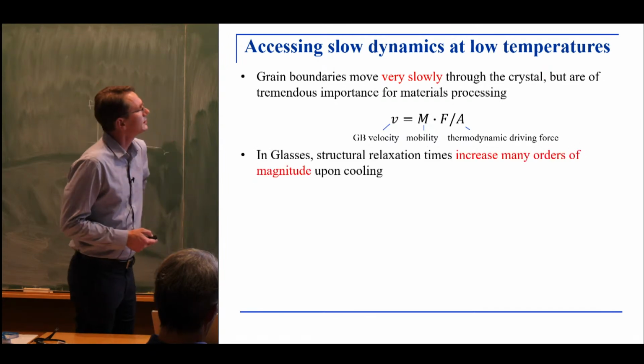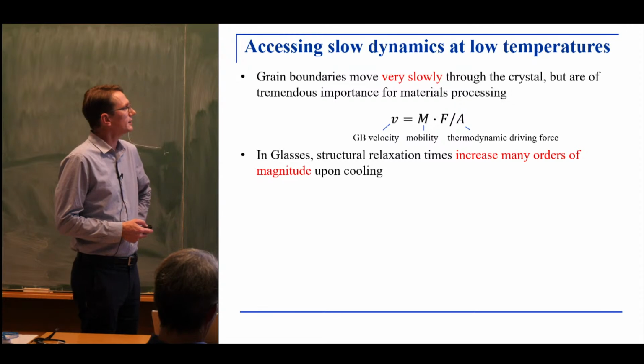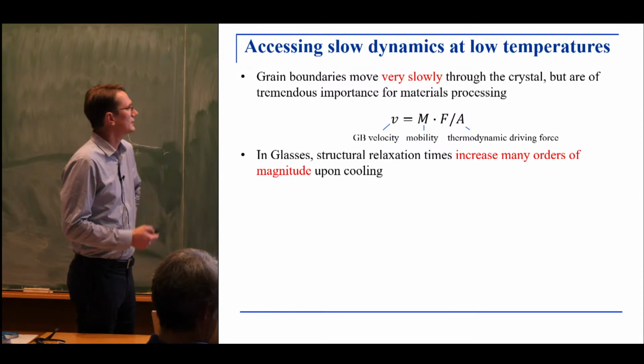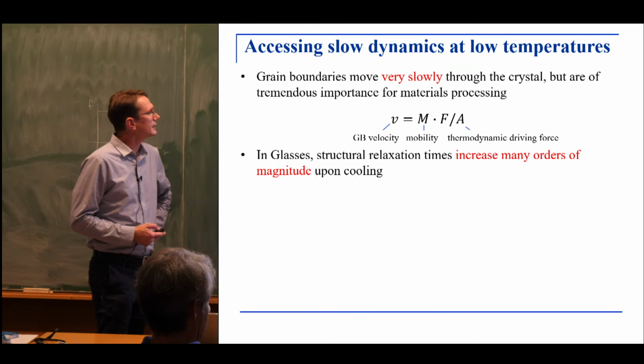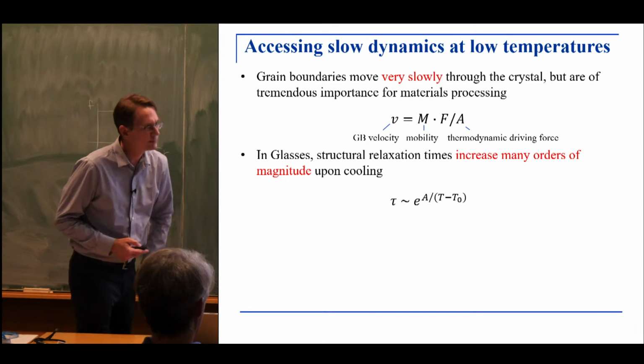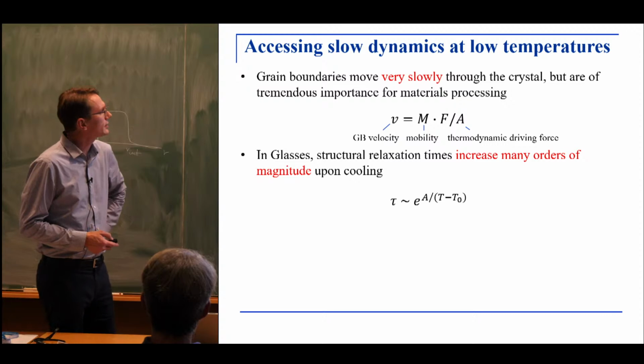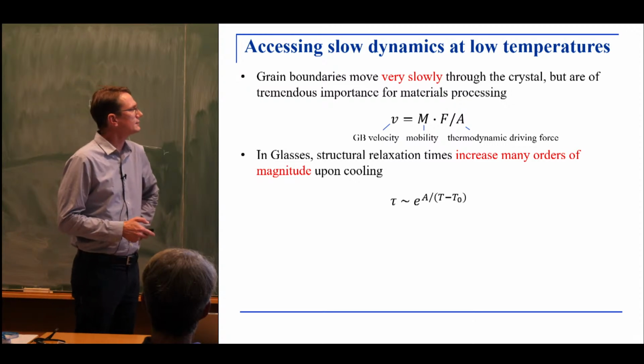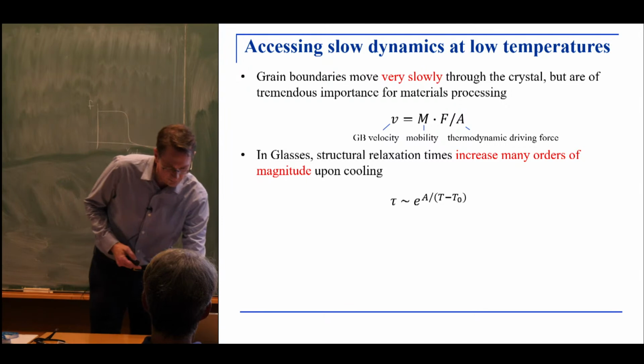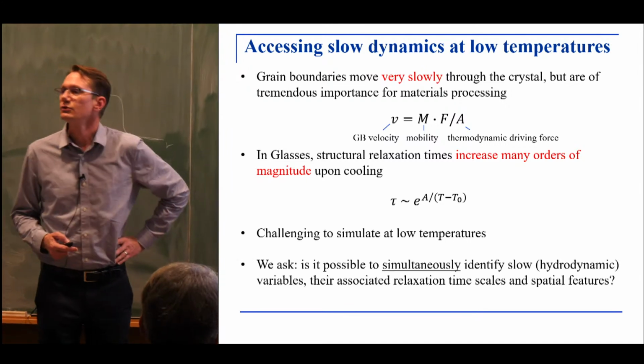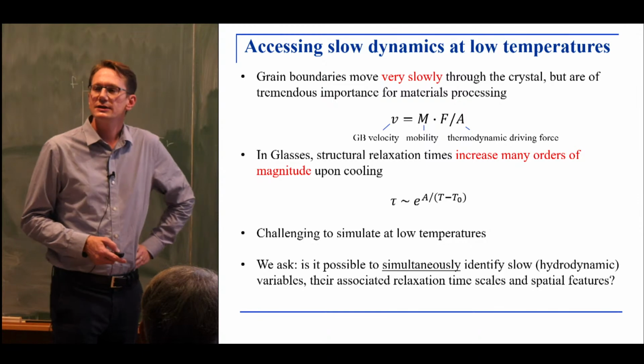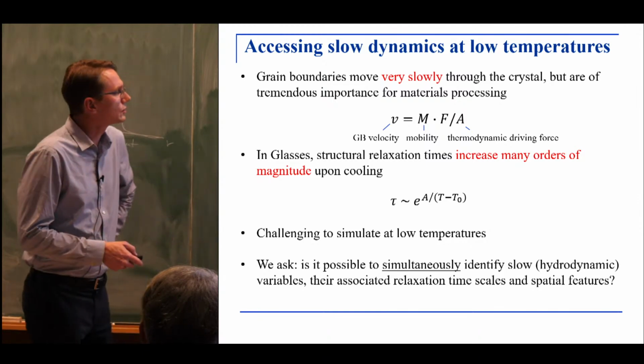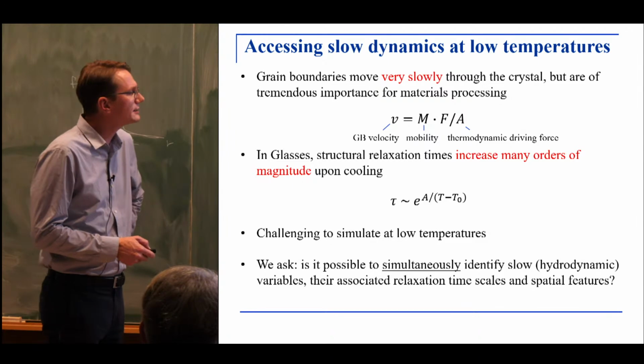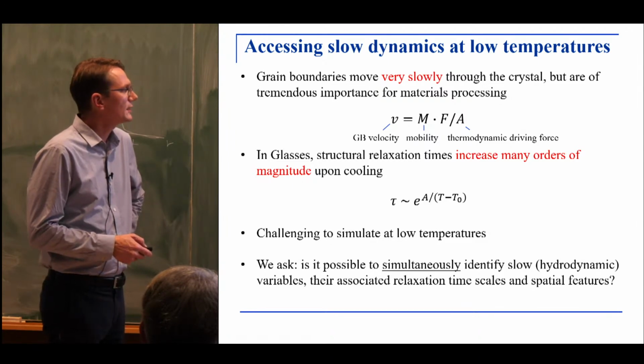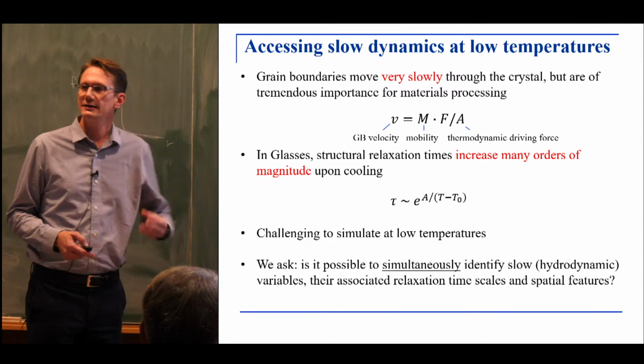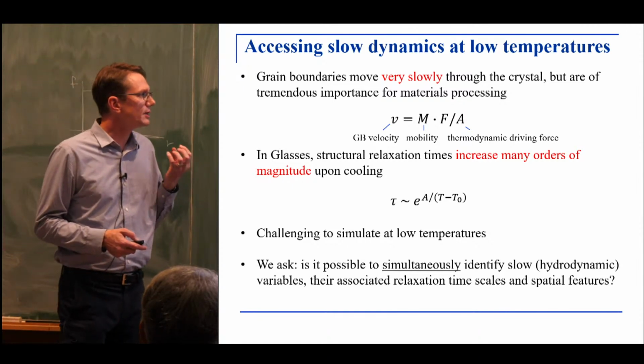And in glasses, it was mentioned many times today that the hallmark of the glass transition is that structural relaxation times increase dramatically upon cooling, and phenomenologically this can be described by the so-called Vogel-Fulcher law here, which predicts a divergence of the relaxation time at some temperature, T0. So this is very difficult to explore at low temperatures, and what we want to do in this talk is ask: is it possible to come up with a method that simultaneously finds the slow variables, finds their structural features, but at the same time also gives us information about the dynamics, right?